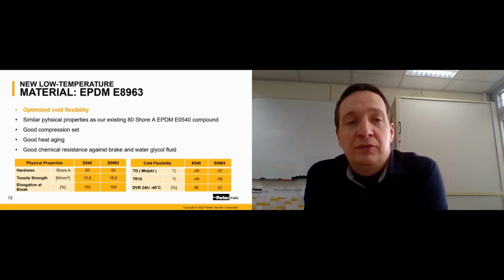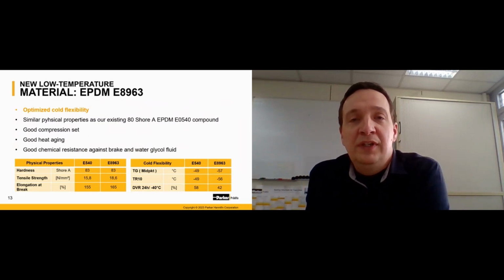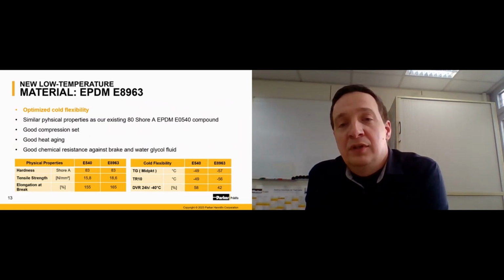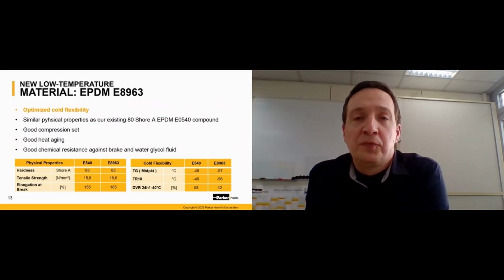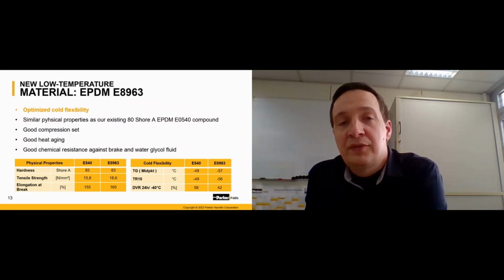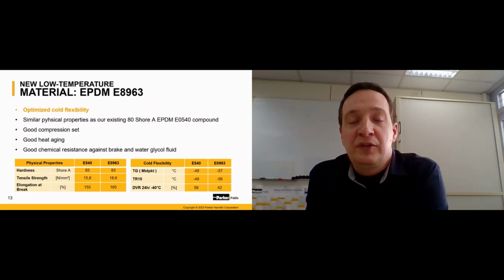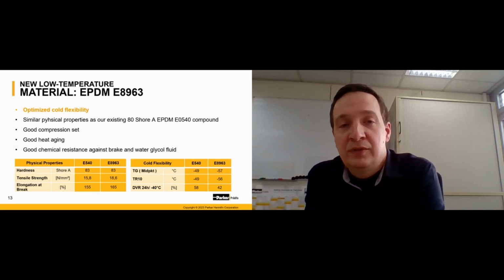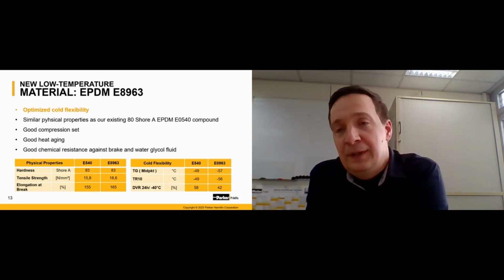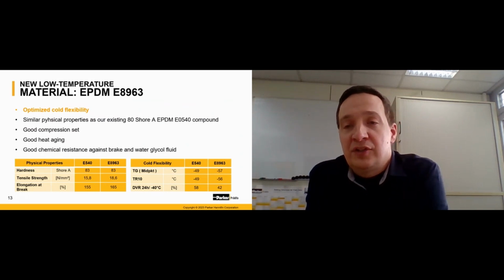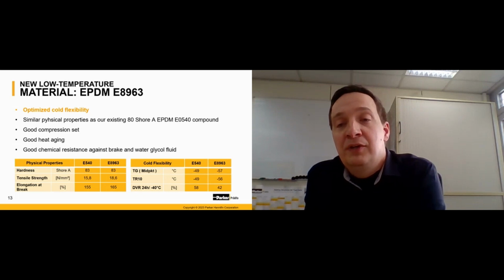Also, I'm glad today to highlight our new EPDM compound E8963. That is a specially developed compound with improved cold flexibility compared to the standard EPDM compounds, without reducing the physical values of that EPDM compound compared to the existing compounds like our E540. As you can see here on the right-hand side chart or table, we were able to reduce the glass transition point from -49 degrees Celsius down to -57 degrees Celsius.